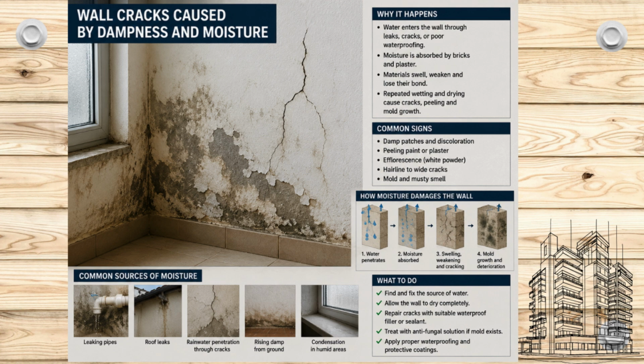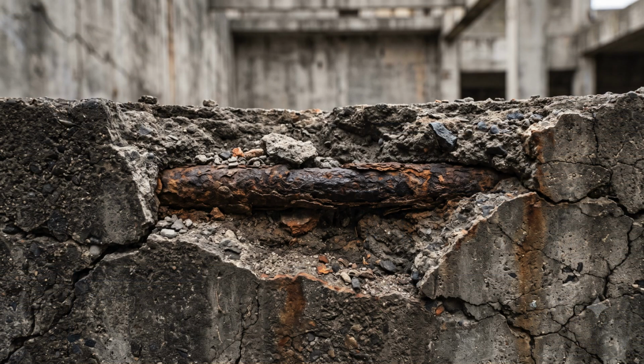For reinforced concrete structures, prolonged water penetration creates an even more serious problem. Moisture eventually reaches the embedded steel reinforcement. Once the steel begins to corrode, rust forms. Unlike steel, rust occupies a much larger volume. As the rust expands, it pushes outward against the surrounding concrete. This internal pressure creates cracks that gradually widen over time. Eventually, pieces of concrete may detach from the surface, exposing more reinforcement to moisture and accelerating the deterioration process. Therefore, repairing only the visible crack without eliminating the source of water leakage is never a permanent solution.